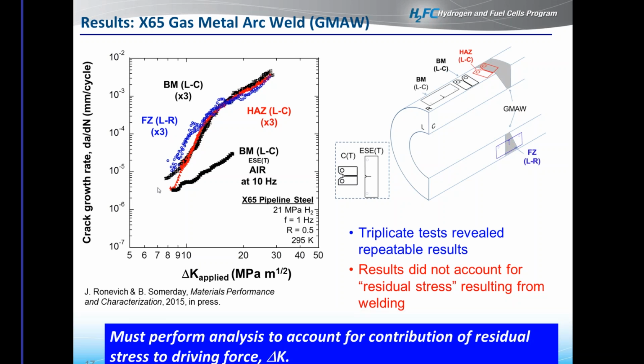But specifically looking at the lower delta K region, which is important because the likelihood of us actually running a pipe at these higher delta Ks, more than likely these are going to be at much lower stresses that we're going to be seeing on the pipe. But nonetheless, you see that overall the fusion zone at the lower delta Ks showed a slightly higher crack growth rate than the base metal did, or the heat affected zone. And then at the lower crack growth rate of the heat affected zone, we actually saw a slightly lower crack growth rate in the red here than we did at the base metal, black.